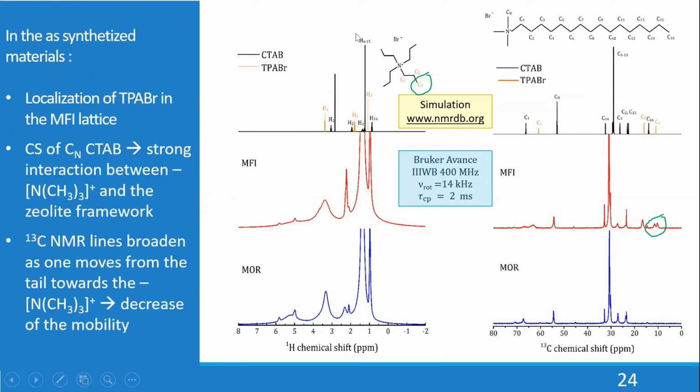First of all, we can see the peaks that correspond to the molecules, but they are broadened due to strong dipole-dipole interaction, because these are molecules confined in solids, and their mobility is restricted. Also, a very interesting peak is here.